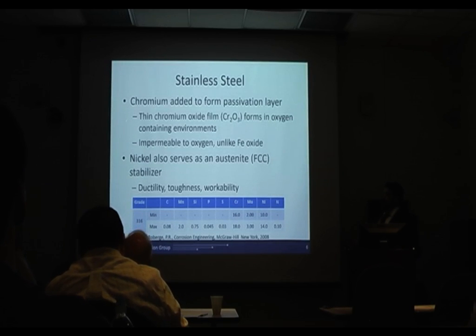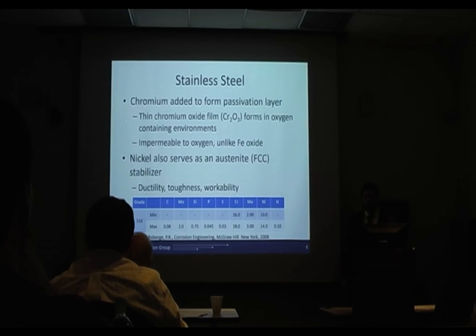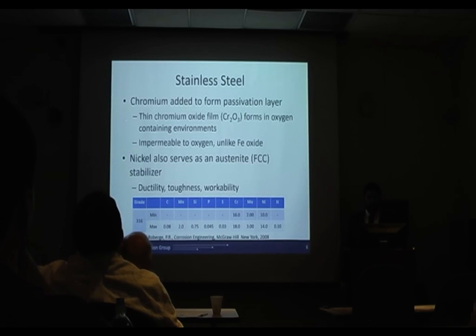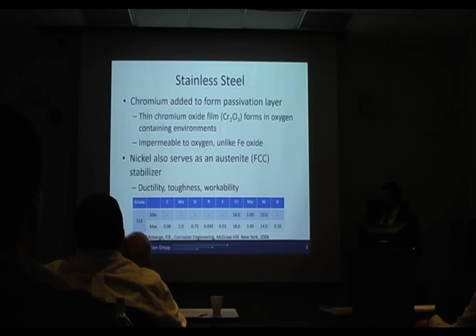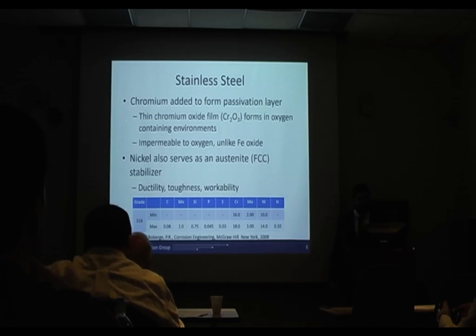So what actually happens is the chromium is added to form a passive layer. When it encounters oxygen in an environment, it forms a very thin layer of chromium oxide. This is impermeable to oxygen, unlike the iron oxides that form, so it prevents further attack by oxygen. Nickel is added to stabilize the FCC structure instead of the normal BCC structure at room temperature, and this increases the ductility, toughness, and workability.